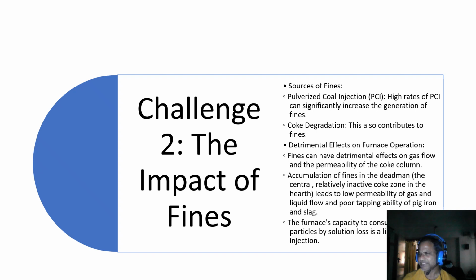Coming to challenge two, another critical challenge that significantly impacts blast furnace operation is the presence of fines. The impact of fines we are going to analyze, along with the causes of fines. These small particles can originate from various sources. For example, pulverized coal injection, especially at high injection rates, can lead to a significant increase in fines generation.